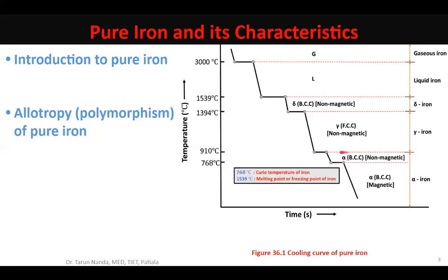And after some time, this represents the time period that would be taken for transition of BCC crystal structure to FCC crystal structure, or in other words, the time taken for transformation of BCC alpha iron into gamma iron. But no sooner is the stipulated period of time over, you have again one phase in your system, and that is called the FCC iron, or the gamma phase, and the iron as such is called gamma iron.